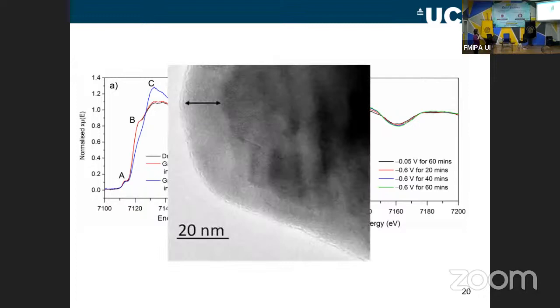What we also did was we took some of the sample after we'd done these experiments, so after we'd applied the potentials, and we looked at them with high resolution TEM. And what you can see is we have a kind of core-shell type structure. So we have the core of the material, still looks like greigite. It's difficult to see, but there are kind of lines in here that you can see, which are the lattice of the greigite. So it shows the greigite is still there in the middle. But then on the outside, we have maybe about 10 nanometer thickness, lighter region, which is all very amorphous. It's not crystalline, which we think is the hydroxide on the surface. So the greigite stays in the middle. It's not changed, but the hydroxide is on the outside.